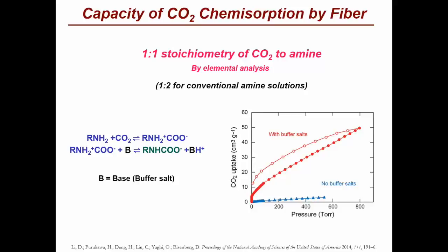They also confirmed this hypothesis by doing experiments in the presence and absence of buffer salts. And it was found that when no buffer salt is present, there was no CO2 absorption. And it was only when the buffer salts were present, which can act as a base, that CO2 absorption was observed.